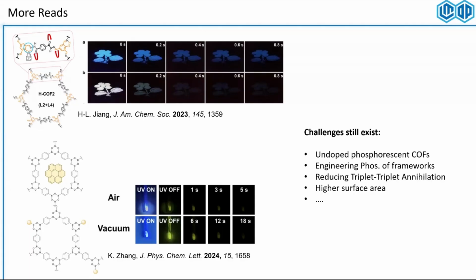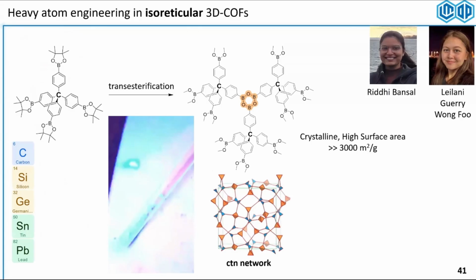How can we have higher surface areas? 500 is in the lower range of covalent organic frameworks. There are many more porous compounds. In fact, recently our students who are sitting at the back synthesized a COF that has nearly 3,000 meters squared per gram of porosity. So this is ongoing research now in my research group, where we started working on 3D COFs, essentially getting inspired by the phenylene diboronic acid 2D COFs and trying to convert them into 3D COFs, which are known when we have a carbon there, but not through transesterification. People could not make anything more than silicon in there because the boronic acids become really difficult to work with and insoluble. Now, using our transesterification method, we already generated germanium-based COFs.